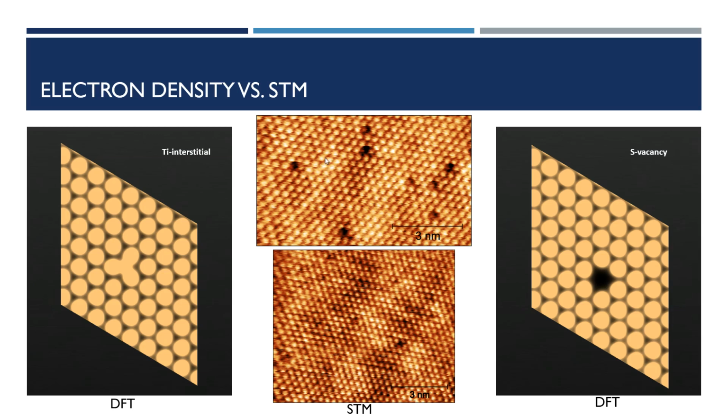And so, given that we have electrons tunneling from the tip to the sample, these electrons are more likely to tunnel onto the positive regions. And since we know sulfur has the oxidation state of -2 and is looking to add electrons in its valence shell, then we argue that these brighter spots will represent the sulfur atoms here.